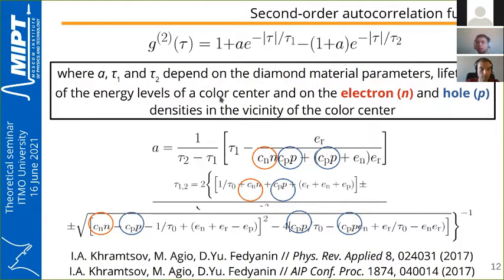But unlike the optically pumped three-level system, it has the dependence of the electron and hole densities in the vicinity of the color center. You can see that we have this Cn times N, Cp times P in the expressions for A, tau1, tau2.